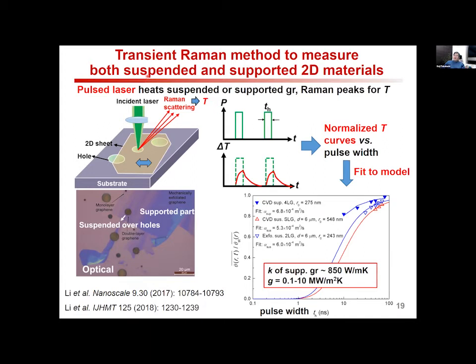Previously I explained the suspended graphene only, but for practical application, supported material is more important. By using our transient Raman method, we obtained the thermal conductivity of supported graphene. The data is 850 watts per meter Kelvin. This is less than half of the large area single layer graphene due to the effect of the substrate. The substrate limits the vibration of the graphene atoms.